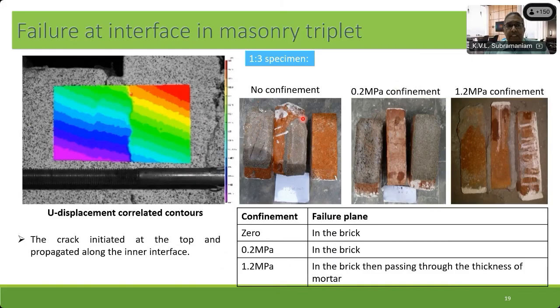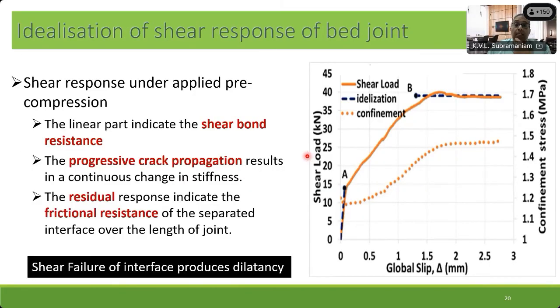So we studied this masonry triplet test further, and we looked at the failure that happens. Invariably, what we saw was that the failure happened at the interface between the brick and the mortar. But with increasing confinement, the failure started happening in the mortar itself. Now, what I want to show you here is that shear failure at the interface is actually quite a complex phenomenon. What is plotted here is a double Y graph. This is what we typically get from a triplet test. Here, the axis on the left shows you the shear load that I'm applying onto the triplet, and on the right-hand side, I'm showing you the confinement stress.